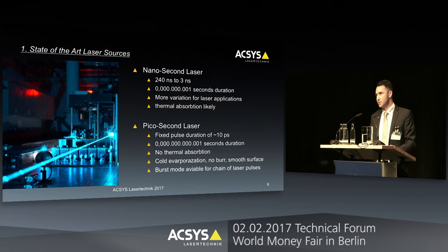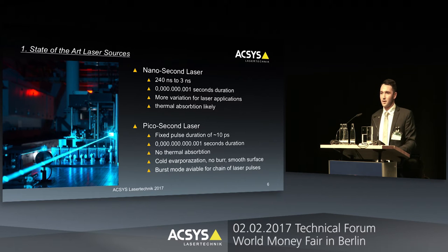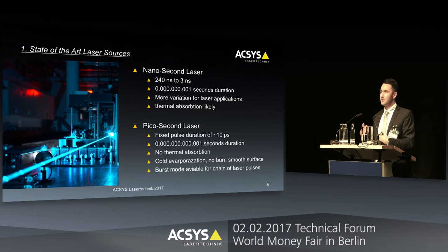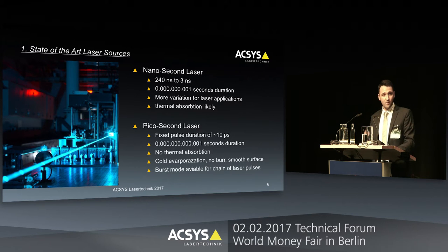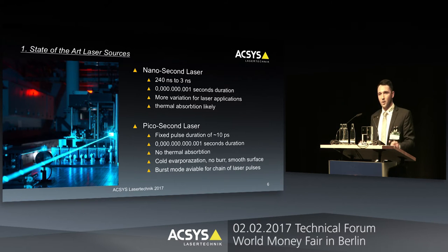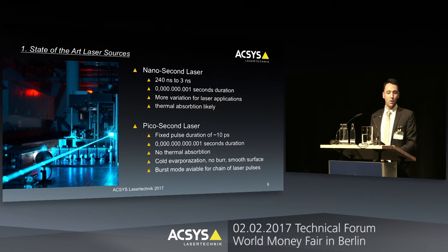The second laser source is the picosecond laser. It works with a fixed pulsation of approximately 10 picoseconds. This time frame is again three digits shorter than a nanosecond. Because of this short time frame, we will create no heat affected zone and no thermal absorption in the material. This results in a cold evaporation — a cold engraving with no burr and a very smooth surface.